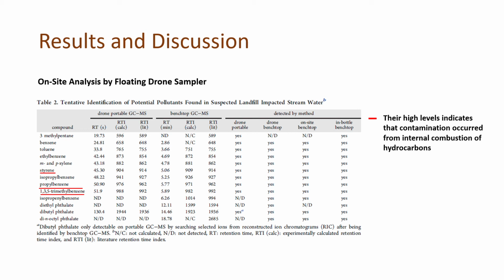It is important to note that many alkyl benzene compounds have very similar spectra, and the peak height ratios generated using the portable GC-MS differ slightly. This is because they used a novel toroidal ion trap mass analyzer and a 70 electron volt electron ionization source, so it differs slightly from the benchtop single quadrupole instrument that is normally used for the NIST spectra. But even so, the match criteria was more than 50%, so it is quite a reasonable result.